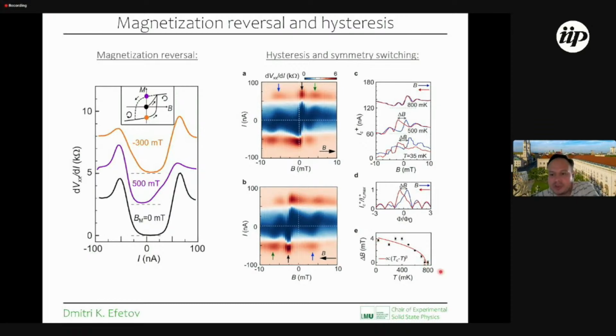identify a critical temperature for the device, for this magnetic phase, which is around 800 millikelvin. And this critical temperature is very different from the Tc of the superconductor. The Tc of the superconductor is around 3 Kelvin, and the Josephson junction just below 3 Kelvin does not show this hysteretic behavior. This only develops below 800 millikelvin, and therefore we think it's basically a sort of magnetic phase with a Néel temperature of 800 millikelvin, which develops in the